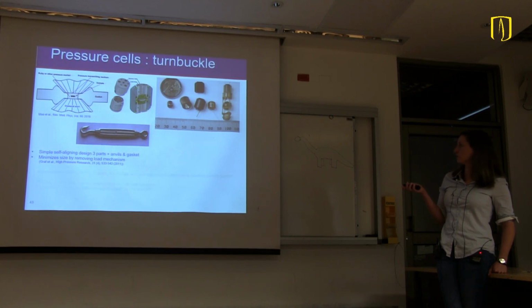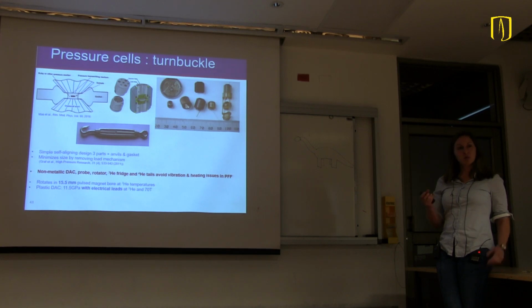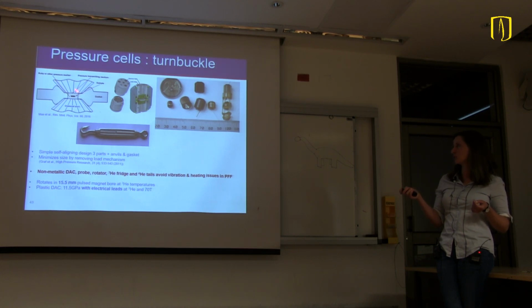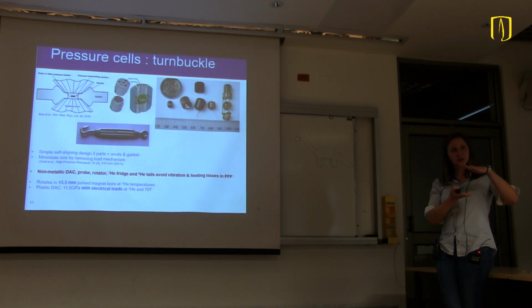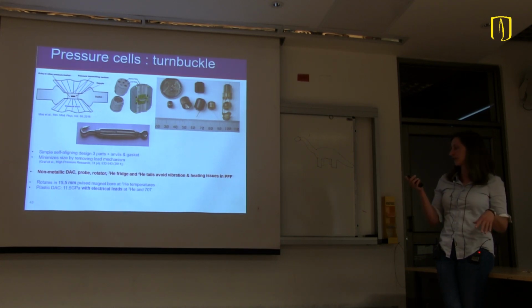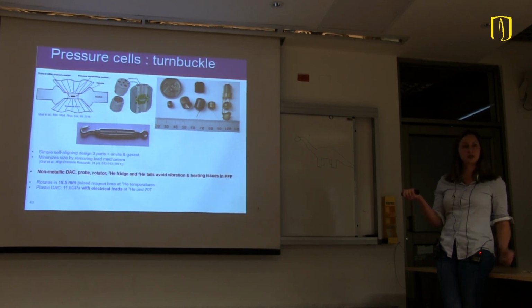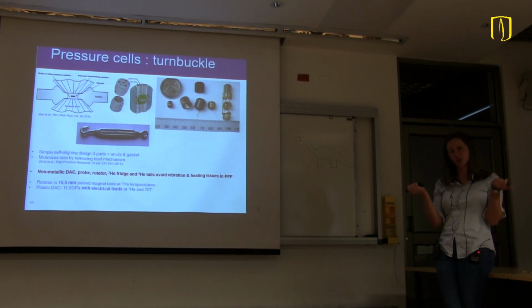Just to talk briefly about those cells. You've seen how bulky those cells are, so you had to find a way to shrink them. What's really crucial for a diamond anvil cell is that you need to have those 2 faces of the diamond really parallel, perfectly aligned, to reach the highest pressures. And he's basically found the turnbuckle principle. Usually you see them in tension, you put wires in tension, but he applied that to put those 2 anvils in compression.